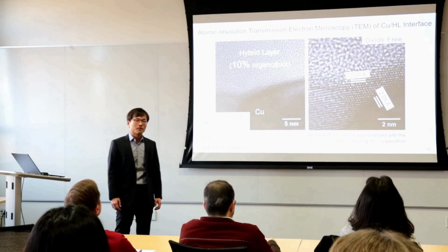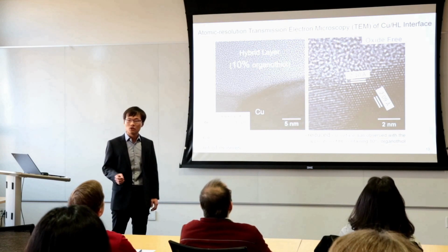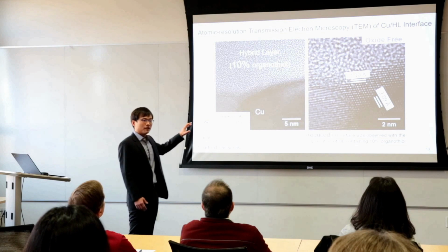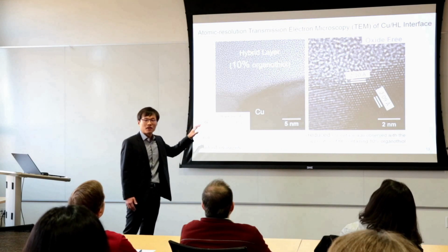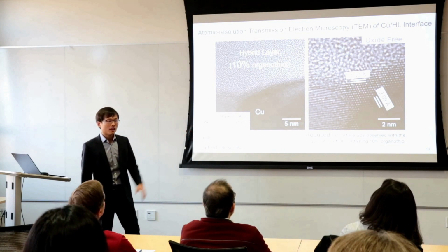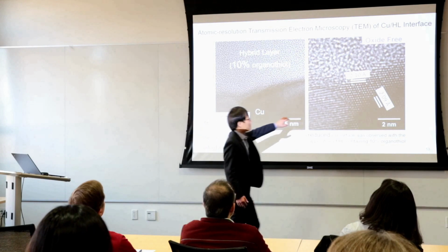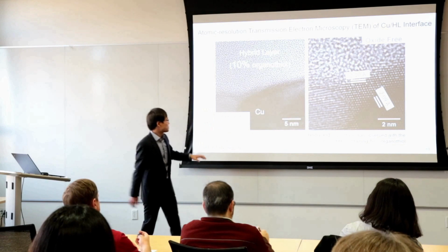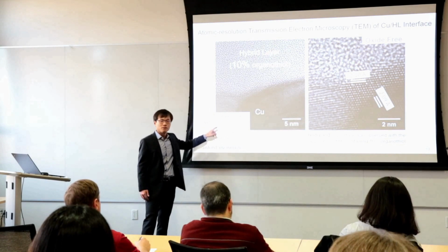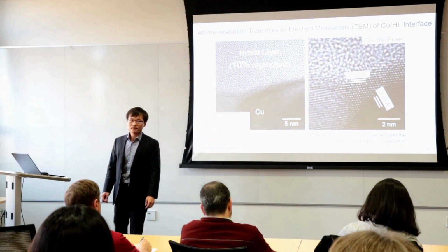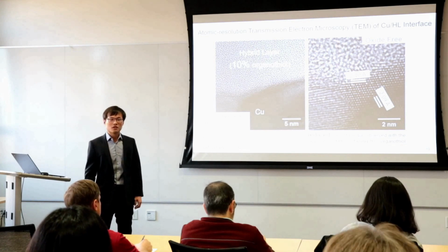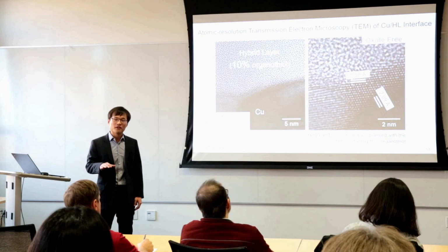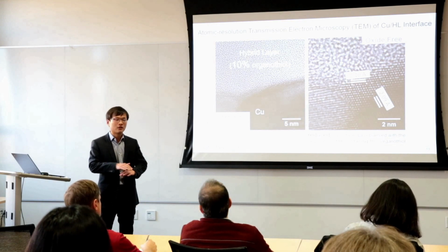This is what happened. With 10% inclusion of organosilyl into the hybrid layer, the copper oxide is absent. And that's evidenced by the measured lattice spacing of 2.10 for the surface of that sample, which matches nicely with the value of bulk copper. So with this, we provided definitive proof of copper oxide reduction with hybrid layer deposited on copper containing organosilyl.